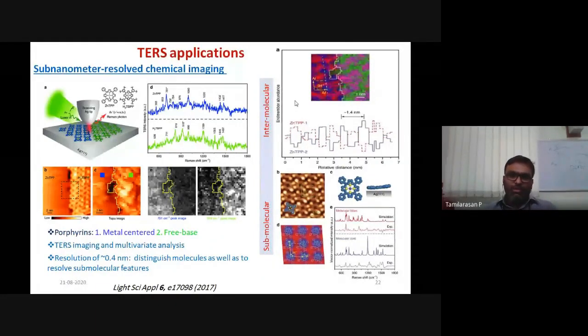But it is not the maximum capacity of TERS. You can even go beyond this. In the same study, they have mapped a plane where you have the same molecule, and they could even go to intramolecular or submolecular level resolution. For example, if you take the metal base porphyrin, you have a metallic center and you have organic lobes. They have simulated the Raman spectrum of the molecular lobes and metallic molecular core, and they also identified the Raman spectrum experimentally for the lobes and the core. You can clearly see they are matching very well.